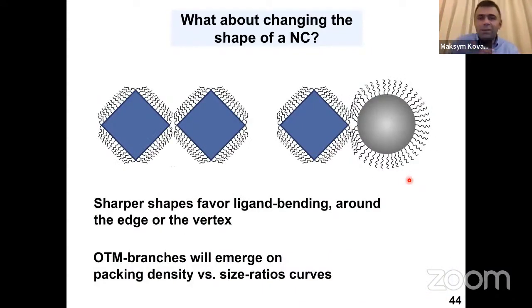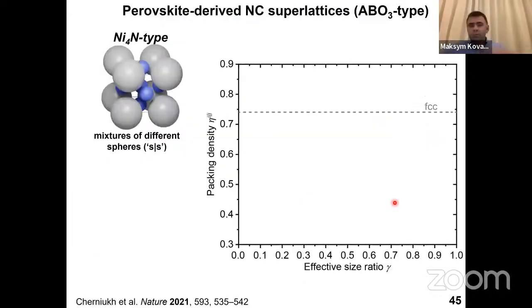Now, when you go to anisotropic shape, or actually it's isotropic, but a sharper shape, a cube, imagine a cube impinging the sphere with the edge. This sharp contact will very likely lead to the bending of the ligands so that the cube and sphere can come closer to each other. By the way, this must happen also when two cubes approach each other through the edge or through the corner. And this happens indeed. This has a stabilizing effect so that you can have a lattice which is denser than without the ligands bending. And so that's a unique property of these sharper shapes, which allows us to observe new crystal structures.